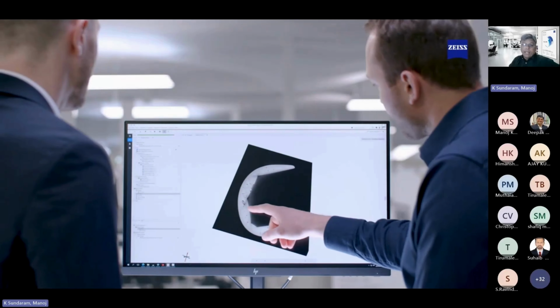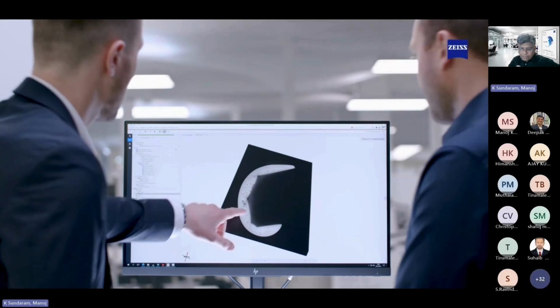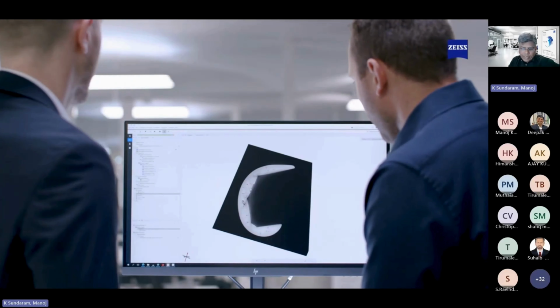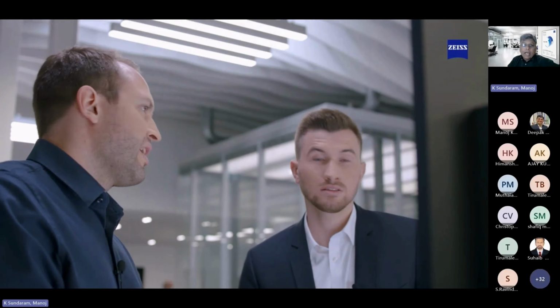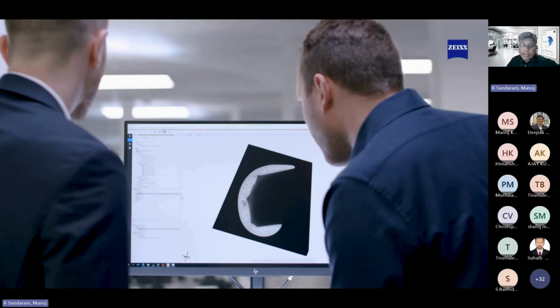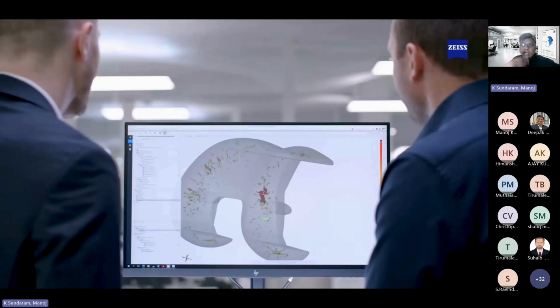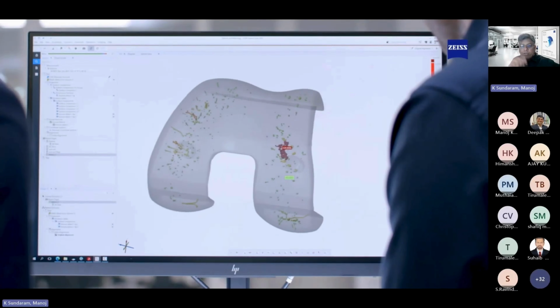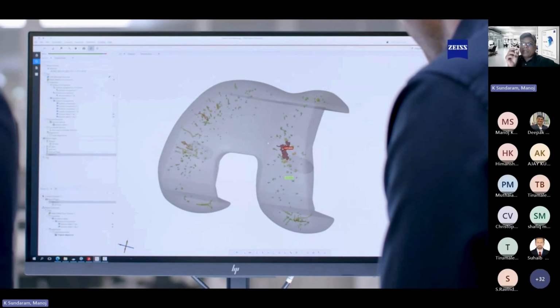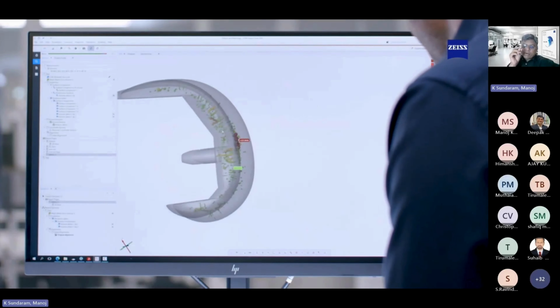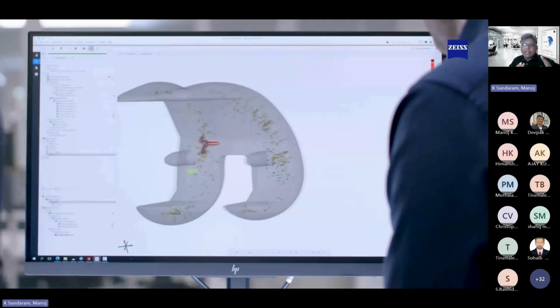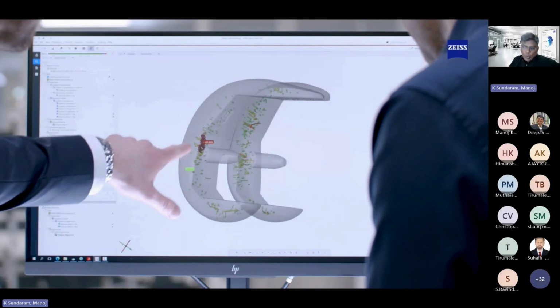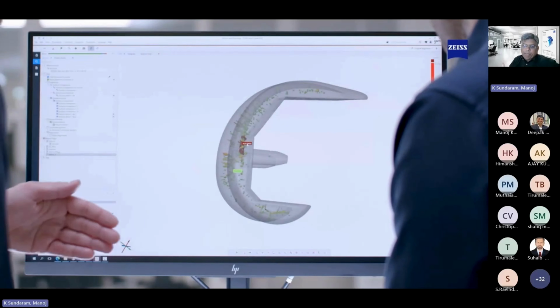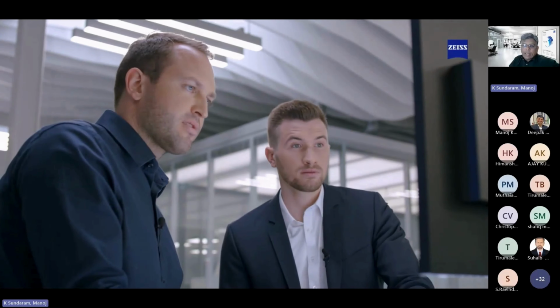So what you see here is 3D data, but they may section it. As you have seen, they have sectioned it out, and they are looking at how the part is inside, how much porosity there is, what is the location of porosity, will the porosity be visible when you machine it, because you need to probably do some post processing. So you can see that we are able to measure the voids, cracks, and represent it in a very nice way for you to look at. This is the power of CT, that you can see a lot of things.